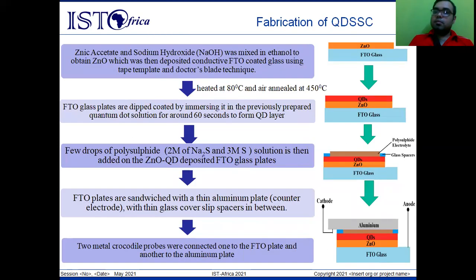Now we come to the main part, that is fabrication of quantum dot solar cell. For fabrication, we first take an FTO glass plate to act as a transparent conducting oxide as a base. Then on that we add zinc oxide. The zinc oxide is deposited in situ by adding zinc acetate and sodium hydroxide in an ethanol solvent. Then it is annealed and heated so that the zinc oxide adheres better to the glass surface.